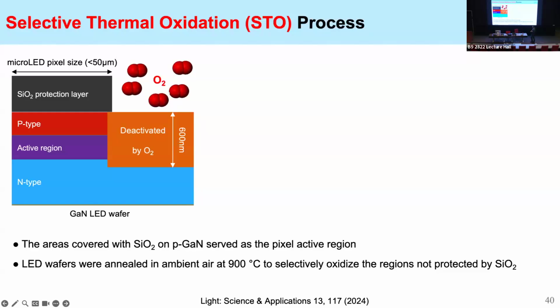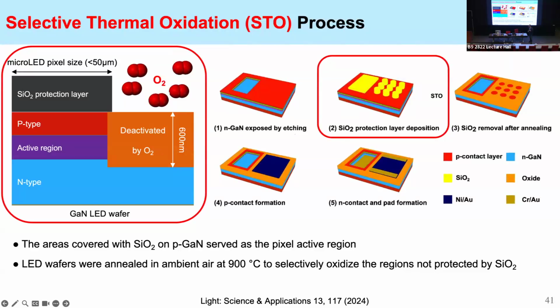However, the area that is not protected by the silicon oxide layer will basically be deactivated, because oxygen likes to oxidize everything, right? So it will oxidize the gallium nitride into gallium oxide, which does not emit light. So by integrating this process as part of the LED fabrication procedure, we will be able to fabricate LED wafers, micro LED, without the use of dry etching.